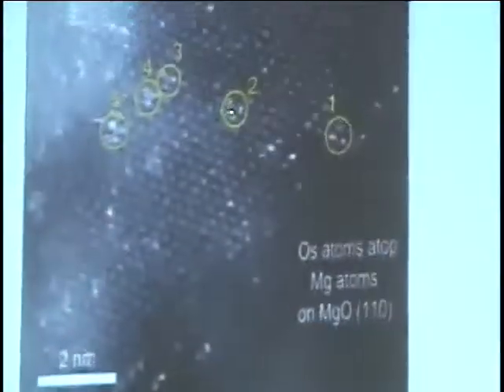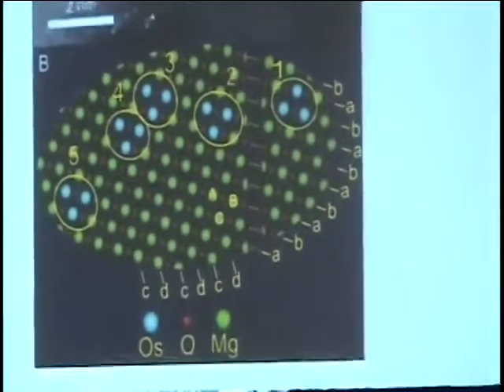To interpret that, one has to assume that there's some distortion of the ligand sphere around the osmium so that the osmiums get close enough to the oxygens of the support to undergo bonding to that support. So we can do the microscopy, as I showed you. We can do the spectroscopy, as I'm showing you, and infrared as well. We can get the distance, compare the distance, find good agreement, and then we can go to a structural model that takes account of the observation from the microscopy, and this is what we didn't anticipate, that even with the triosmium on this 110 surface of MgO, the osmium atoms are atop the columns of magnesium atoms. And so that gives us the key to do structural models.